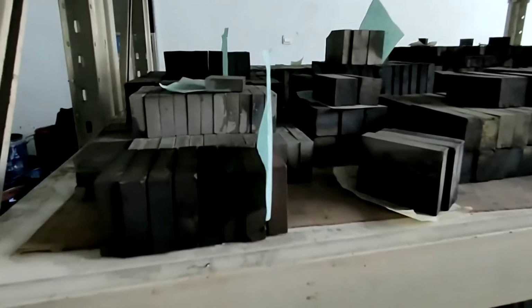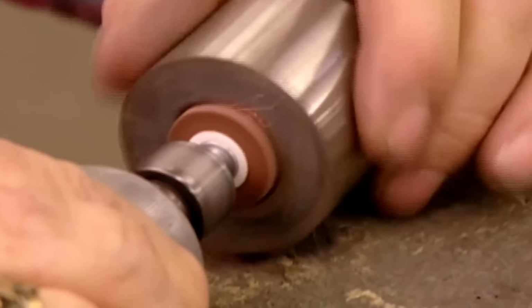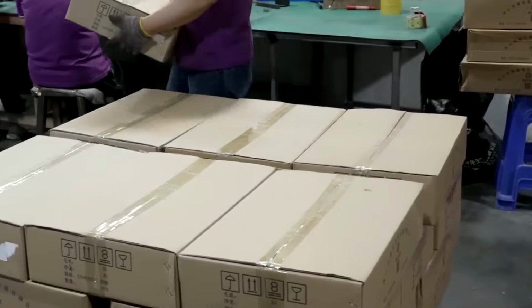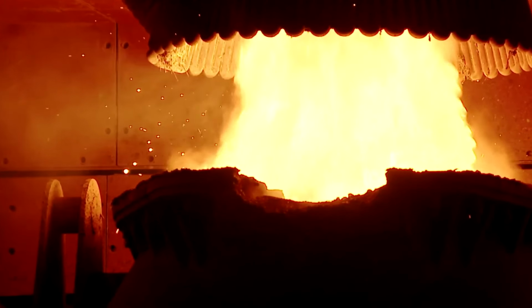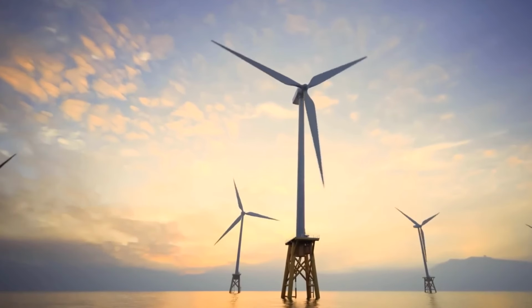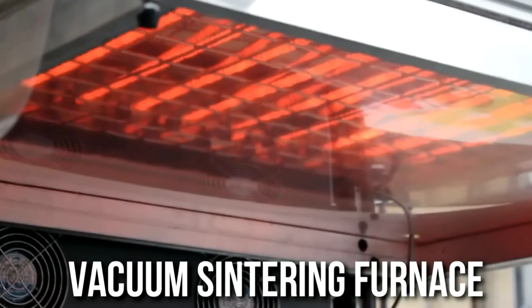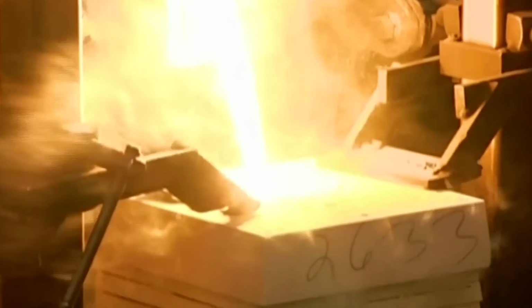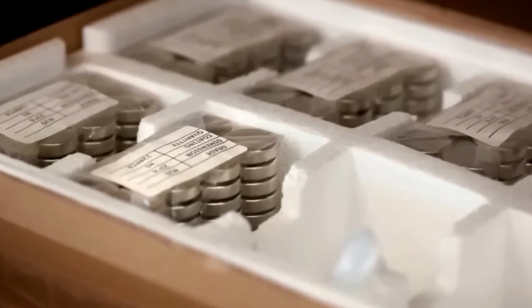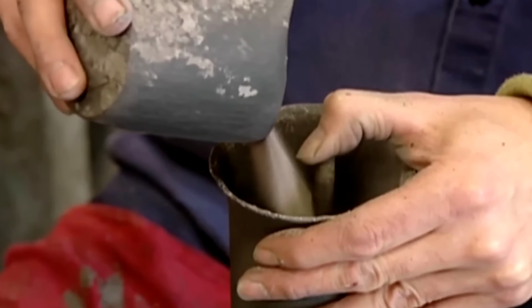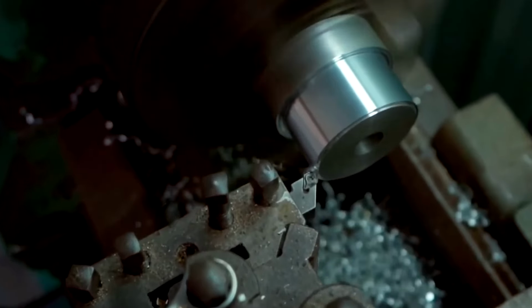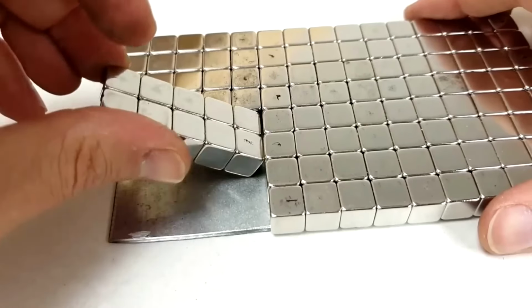During this phase, the material transitions from a porous form into a fully dense solid, achieving nearly 100% of its bulk metal density. Once this equilibrium is reached, the temperature is slowly reduced over several hours, degree by degree. This deliberate cooling gives the crystal structure time to lock in the previously aligned magnetic orientation. Finally, an additional heat treatment at around 950 degrees Fahrenheit stabilizes the entire structure, completing the sintering process.